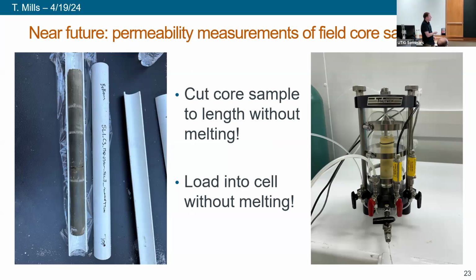And in the very near future, we're going to be taking our core samples, cutting them, and loading them into our cell so we can measure their permeability as well. And then we can correlate our permeabilities with our other sediment characterization properties that we've measured. And then the challenge here is being able to cut the sample without melting it. Every time we've tried to cut a piece of our permafrost, we just created a nice new ice sheet. And so we can't measure the permeability if we melt the two ends. So this might be a little more difficult than it seems, and then try to load that into our cell without melting the permafrost. So that's where we're going in the very near future with this part of the project.